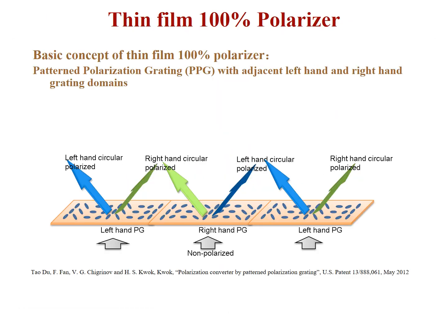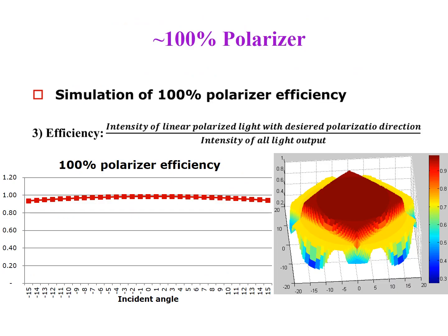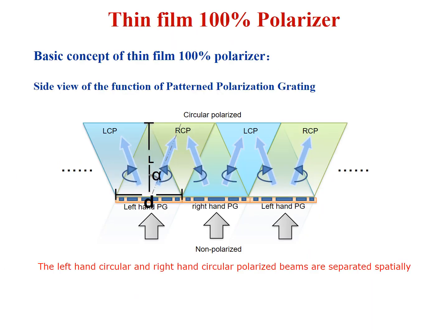If you write down harmonic scattering, then with proper thickness, harmonic diffraction grating, then you can have only two output lights, left-handed circular and right-handed circular light. If you put a quarter wave plate, you can make 100% polarizer. So if divergence of light is plus minus 15 degrees, the polarization intensity will not be 50%, it will be about 97%.